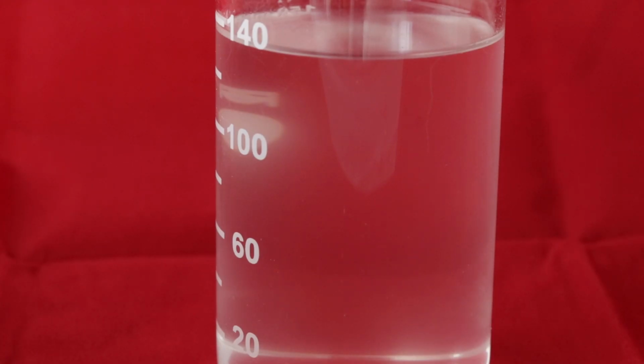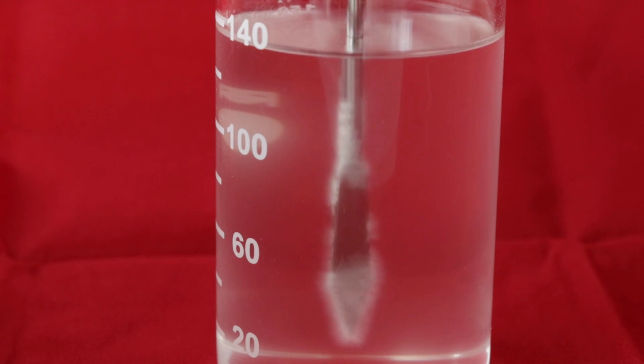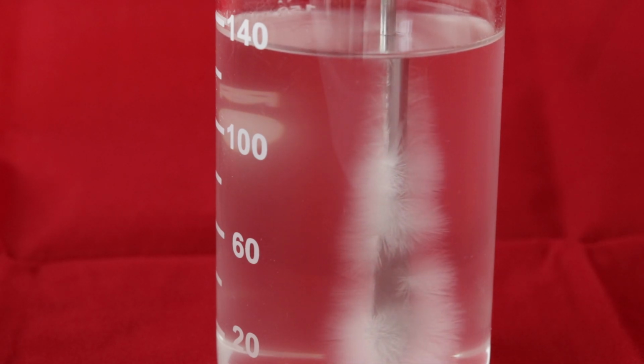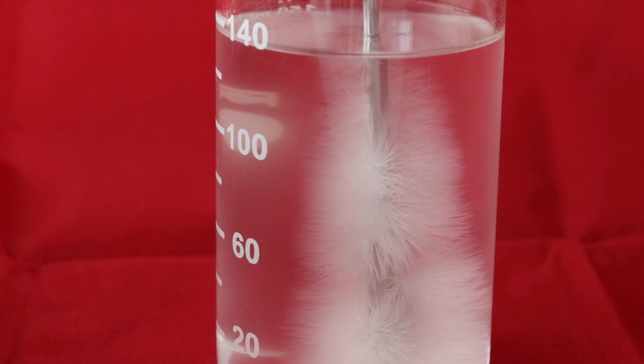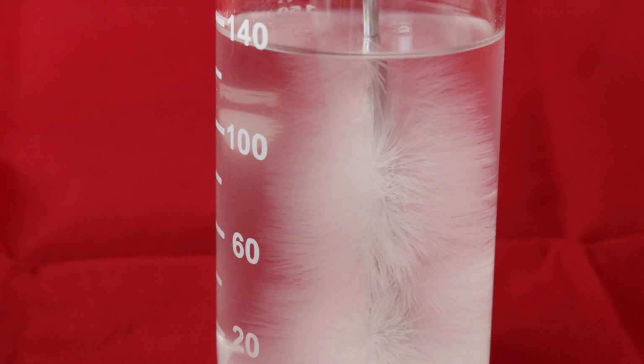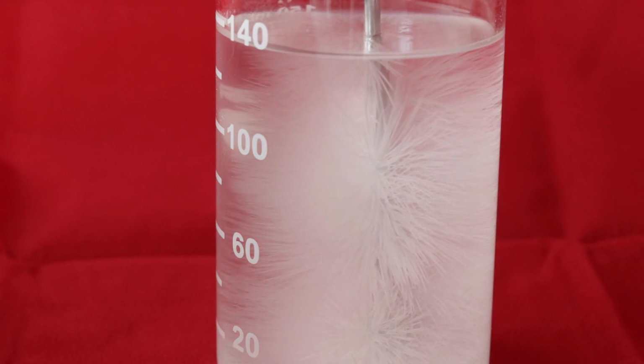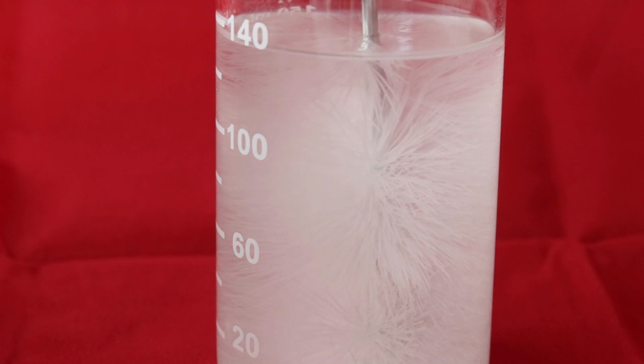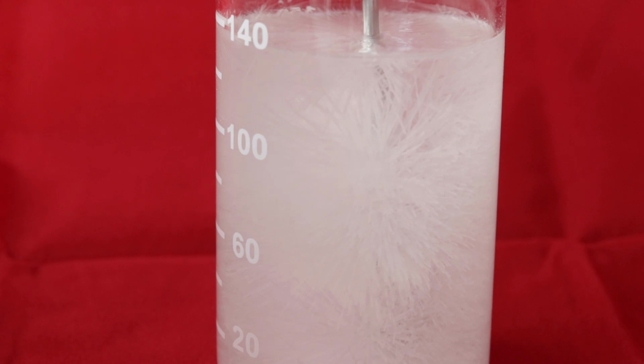The solution in the movie was formed by dissolving around 160 grams of salt in 100 milliliters of water at close to 100 degrees, and then slowly cooling it to 20 degrees, to room temperature. Because the solubility of sodium acetate in water at 20 degrees is only about 46 grams per 100 milliliters of water, the solution is supersaturated.